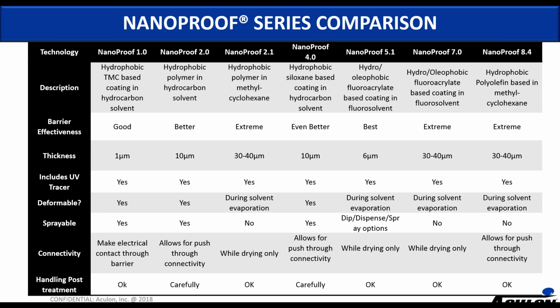And then on to 7 and 8.4, also 2.1, which are our most robust coatings. In general, they're 30 to 40 microns thick. They have a special feature that allows them to hold their thickness around the edges of three-dimensional components, which is really what gives them the edge up on anything else that's out there. So you could have a 30 micron thick coating on the top and on the bottom of your component, and then the edge is not going to vary by more than a few microns. It may be anywhere from 28 to 32 microns in thickness. Maintaining that thickness over the edge is what allows you to get protection.